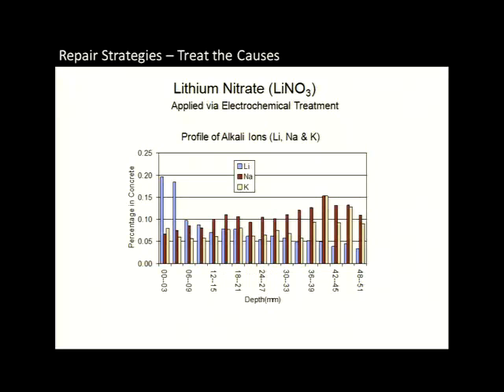This shows you a graph, again represented in a slightly different way, a bar graph, the percentage that we would need in concrete for the lithium here on the y-axis, and the depth in millimeters. What this is showing is a range of depth, so 0 to 3 millimeters, 6 to 9 millimeters, and all the way up to a 48 to 51 millimeter depth. So that's getting up to about 2 inches into the interior of the concrete. The great thing about this is that we see that we can get lithium in. Lithium is the lighter purple, or the far left bar.